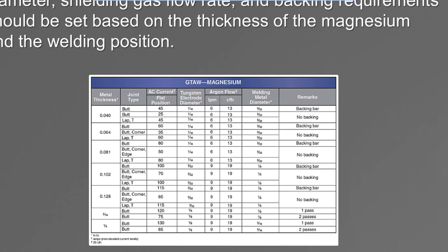Okay, so AC can be used with helium, argon, or an argon-helium mixture when we weld metals 0.20 to about ½ inch thick. Okay, you can also use DC electrode negative (DCEN), but there's no cleaning action, but there's better penetration. With helium, especially when welding thicker stuff, it's a lot better. Okay, so I've seen and used helium and DC electrode negative (DCEN), and it's kind of cool. Okay, so magnesium also requires a preheat and a slow post heat to avoid cracking.